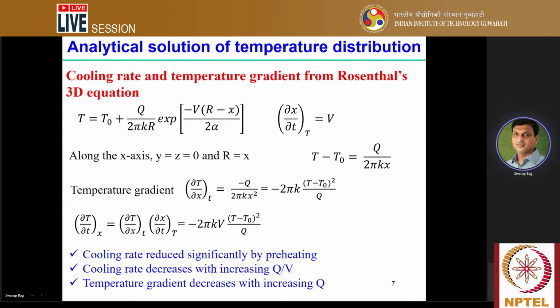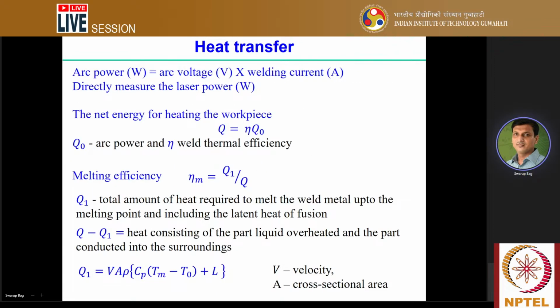There is another part also: the overall heat balance in a welding process, and how to consider the different parameters. One is the arc power. How do we calculate the arc power? That is equivalent to the arc voltage times the welding current. The multiplication of these indicates the arc power, in watts. In the case of a laser, we directly measure the laser power. But in the case of arc welding, we measure the arc voltage and the arc current, and then we calculate the arc power.